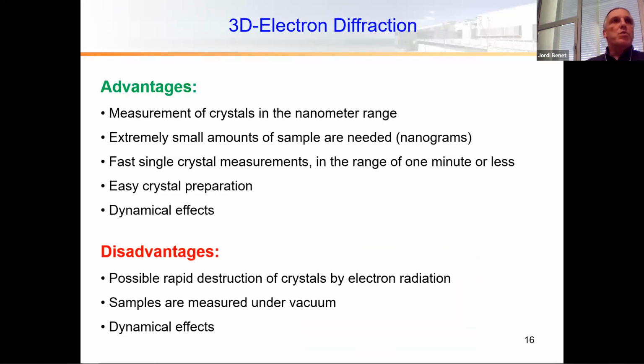Which advantages, in my opinion, does electron diffraction have? Of course, the measurement of crystals in the nanometer range. We can also use extremely small amounts of sample, just nanograms to be able to perform a measurement. We can do fast single crystal measurements, as I said, in a range of a minute or less. We have, in a standard case, easy crystal preparation. And I see also as an advantage the dynamical effects.